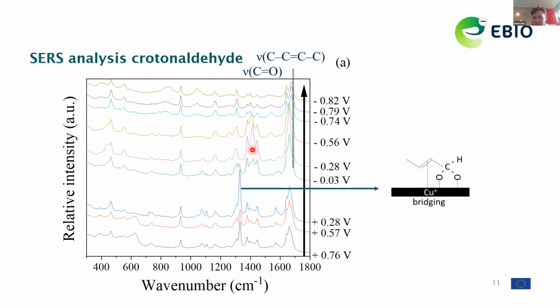But I think the most important thing to point out to you is that now we can clearly see peaks here, Raman bands at about 1680, 1700 wave numbers, which is indicative of both the C=O of the aldehyde and the C=C of the aldehyde. And the fact that these intensities are so large is evidence that you do get a significant adsorption of the